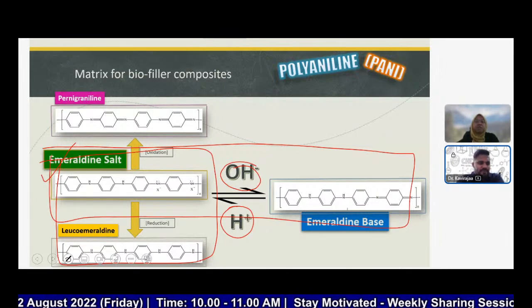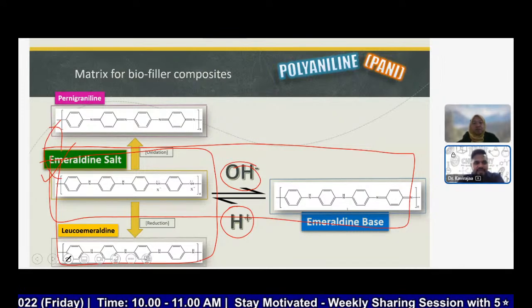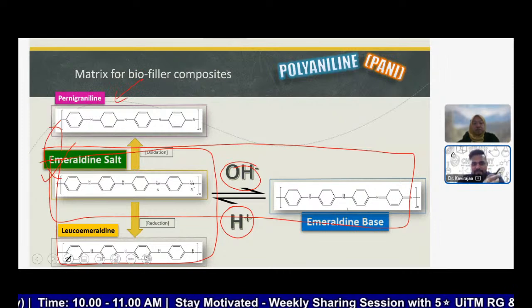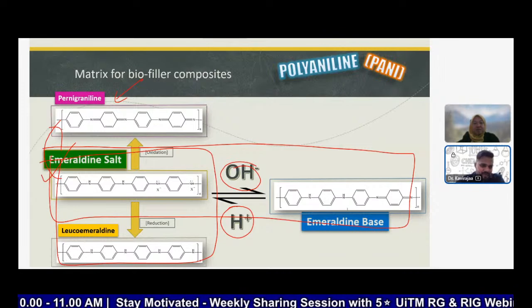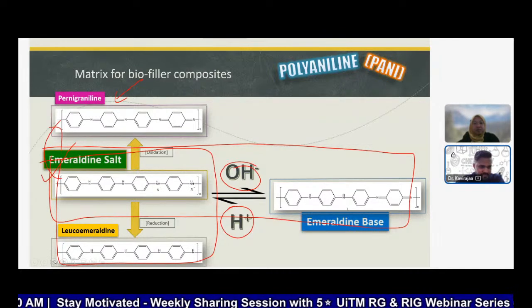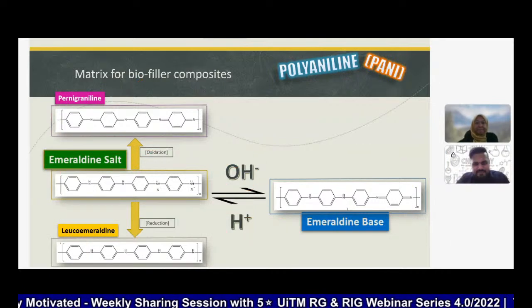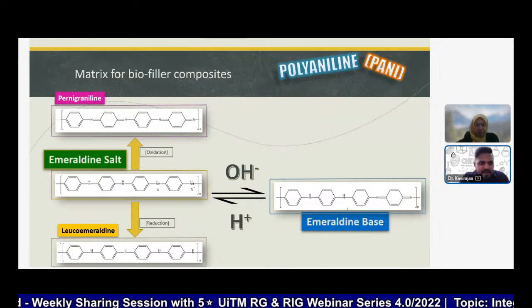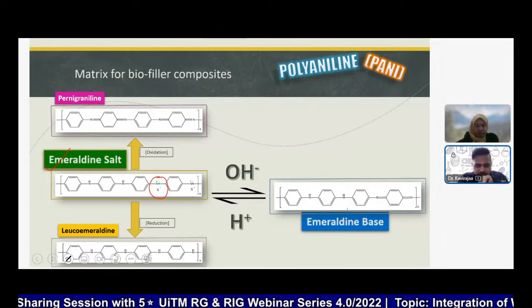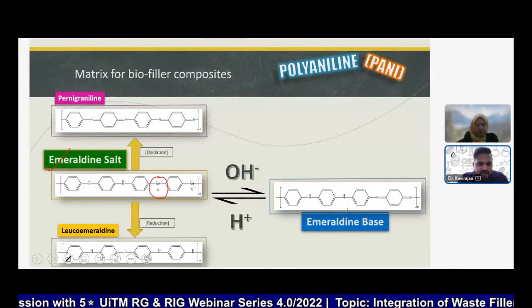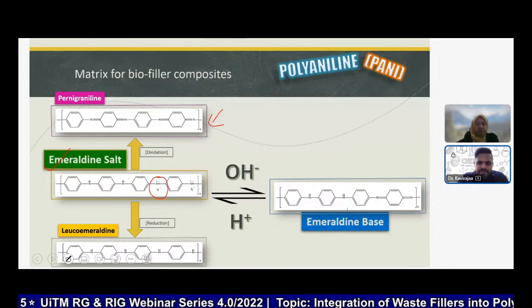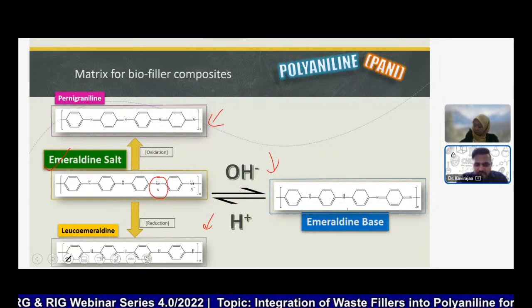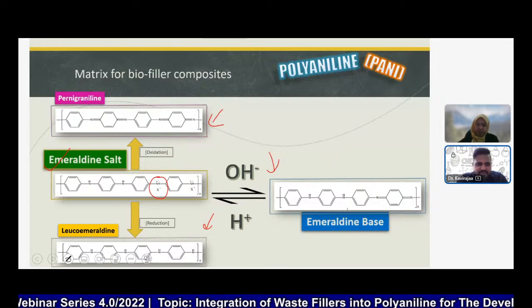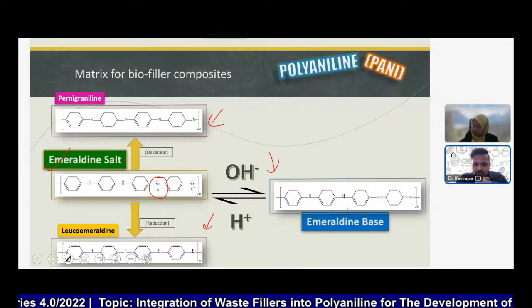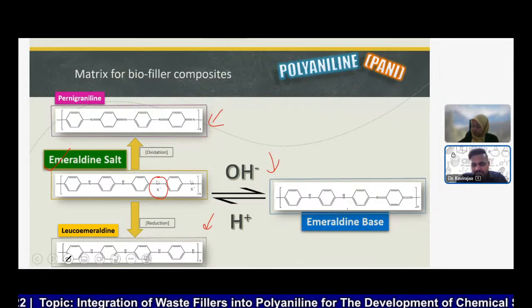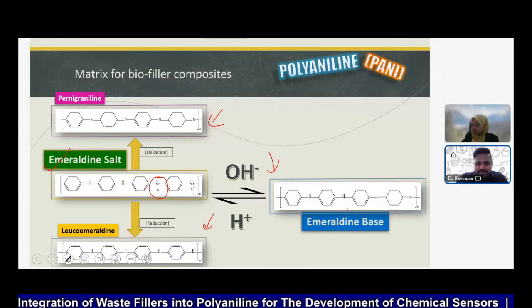And on the other side, we also can make it fully oxidized. When we fully oxidize it, it is known as pernigraniline, and it will be kind of a purplish color. Okay, now. So if we look at these four different structures of polyaniline, only emeraldine salt has these polarons. We call these polarons. And also we can see the conjugation appears compared to this structure or this structure or this structure. So pernigraniline, leucoemeraldine or emeraldine base, these structures might have conductivity, but it might be very low or maybe no conductivity at all. But emeraldine salt will have a certain degree of conductivity, and this conductivity depends on how we prepare it, how pure it is, and so on.